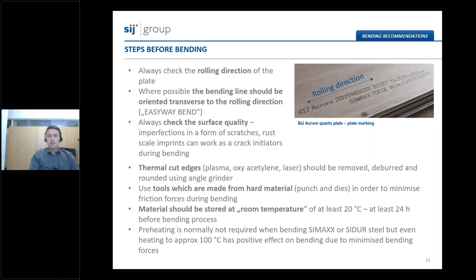Then something about the storage of the material. We all know that the material can also be stored outside the workshops. Problems can appear during the winter when the temperatures are relatively low, so below 0 degrees C. And in this case, you should move the plates from the outdoor storage into the workshop at least 24 hours before bending. With this step, so with the moving of the plates into the workshop, you can effectively minimize the appearance of cracking.